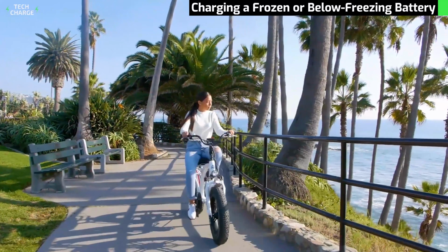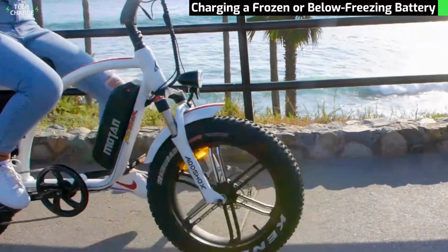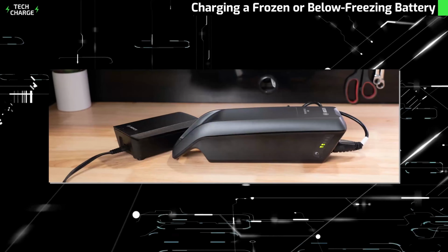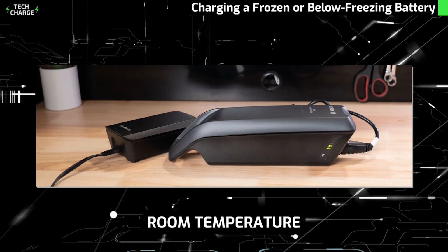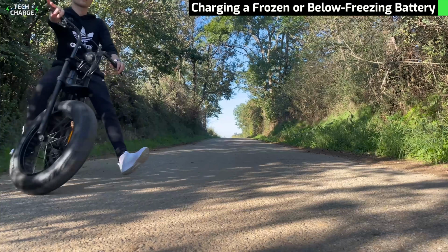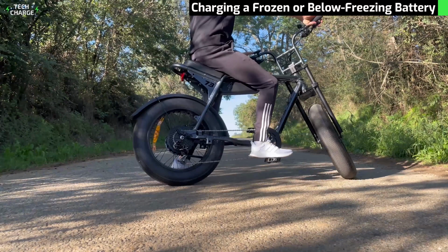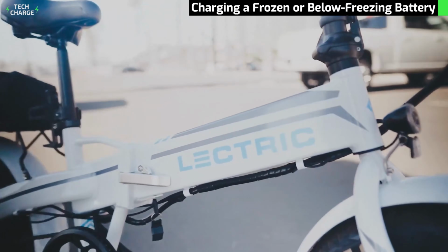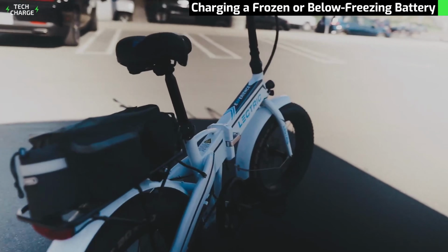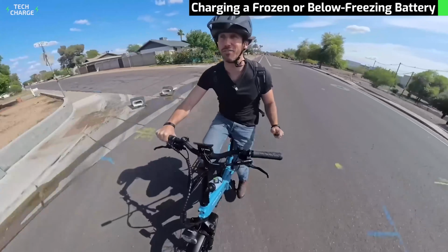The correct procedure takes patience. Bring the battery inside, let it sit for 1 to 2 hours until it reaches room temperature, then charge. If you're in a rush, at least let it warm to 10 degrees Celsius before charging. That's roughly 50 degrees Fahrenheit. Anything colder is asking for permanent damage.